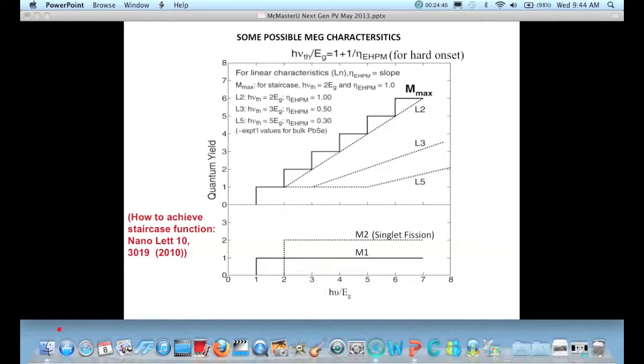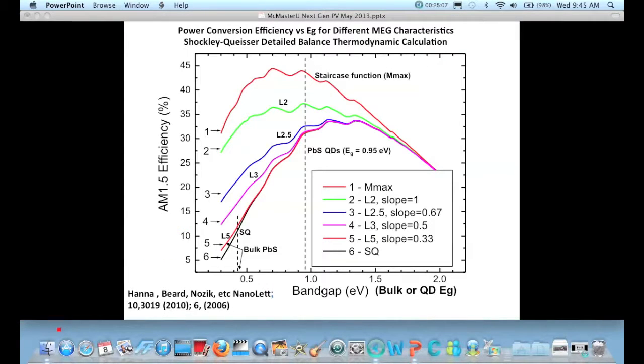So there's this simple relationship between how many electron hole pairs you get per photon when you're beyond the threshold, and that efficiency is simply related to the threshold energy. So these are not independent parameters. And when we do the Shockley-Queisser analysis, shown here in this paper, both for PV and for solar fuel production, you see that you get this significant increase in the maximum possible thermodynamic conversion efficiency compared to what you get in the Shockley-Queisser limit, where you assume that the electrons thermalize and don't use that extra kinetic energy to do useful work.